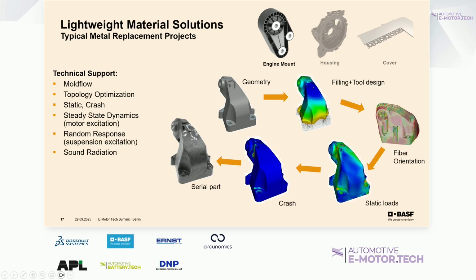But here's also the story. I mean, how does it work? It's not like having one geometry and taking it and making it out of plastics. So it's important to say we start typically with a geometry. If you already have a good plastic design, we could directly step into the filling analysis. The whole workflow here could be done in-house at BASF, so that's some kind of offer we have. We typically check the fiber orientation because for fiber reinforced plastics it's important to know this. And then we also make the kind of static analysis, also crash analysis.